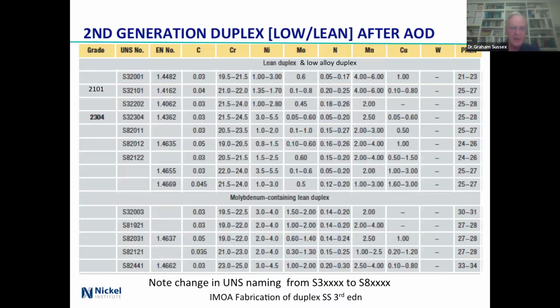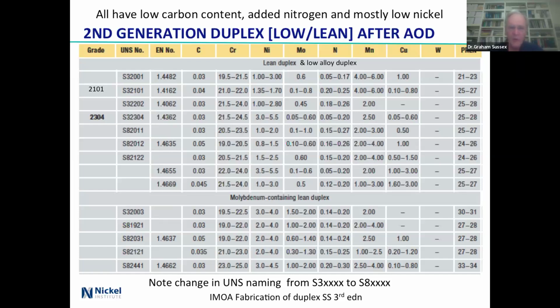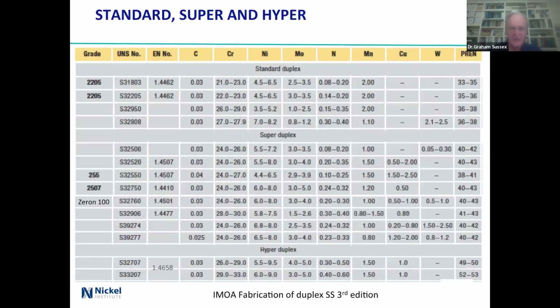Okay, so here we've got the low and lean ones, the 2101, 2304 across there, and look down the side and you see that we've got in the 20s for PRE. So it's better than 316, but it's not as good as full-scale duplex as in 2205. All have got low carbon, all have got added nitrogen, and mostly, as you can look down there and see, there's not terribly much nickel. The moly one's a bit better, bit higher corrosion resistance, but yes, that's the family.